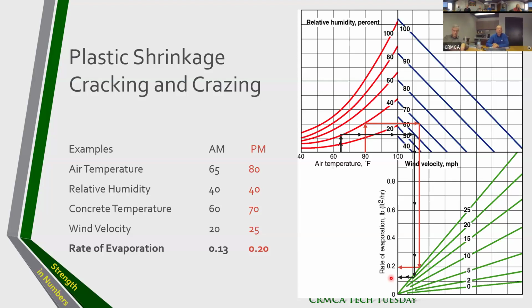If you do the same concrete mix, but now it's mid-afternoon, you are at 80 degrees air temperature, relative humidity is still the same, but your concrete temperature has increased by 10 degrees, because your aggregates got a little bit of sunshine. So with 70 degrees concrete, we go down, wind has increased a little bit to 25, now you're already at 0.2 pounds per square foot per hour.